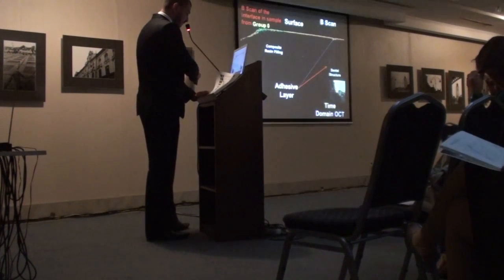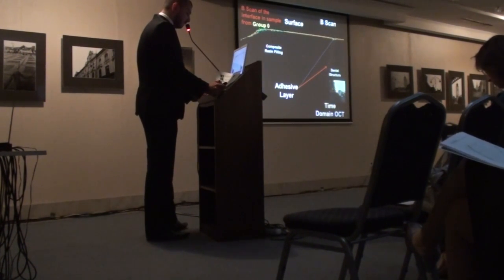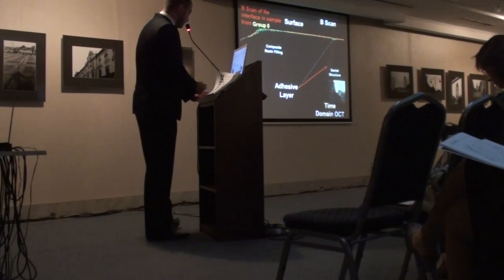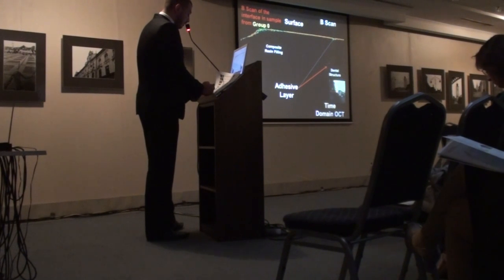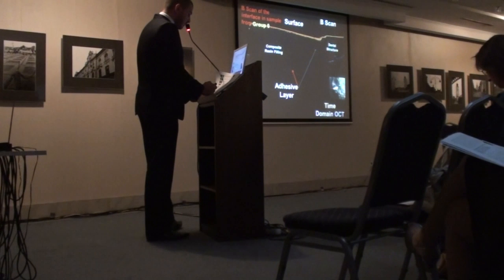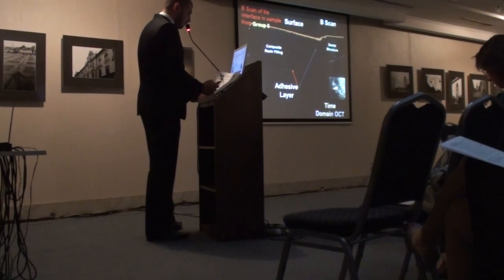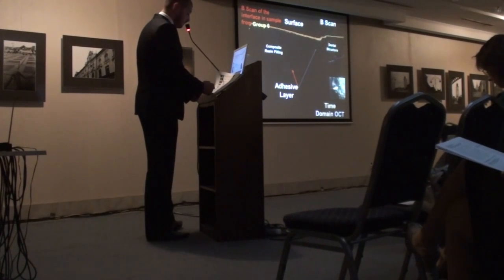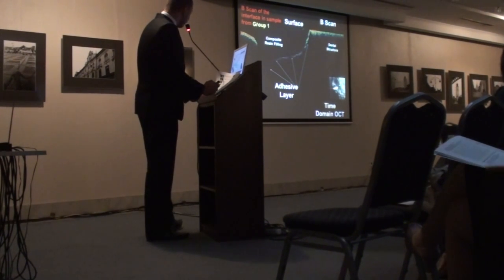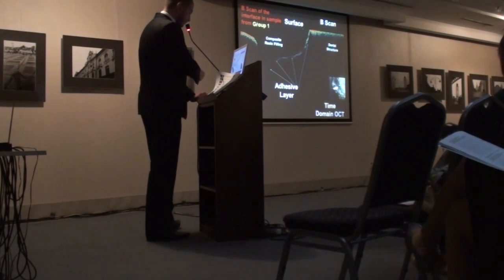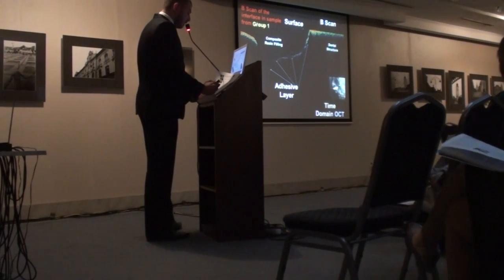On the samples made with normal adhesive, the interface between composite resin filling and the dental structure is hard to evaluate. Another sample with normal adhesive, in which it is hard to observe the adhesive layer and possible air defects. Sample from group 1, in which the adhesive layer was modified with zirconia in a layer.